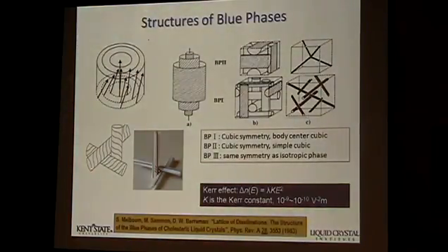So in the past, people very carefully controlled that and studied their physical properties, and they also studied much earlier their electro-optical effects. There are 2 types of electro-optical effects you can expect from such materials. This blue phase material shows a field-induced Kerr effect. What does that mean? The birefringence is a function of applied field strength, proportional to the periodic structure, the elastic constants of the blue phase, and the square of the field. These are Kerr constants, in general in the range of 10 to the minus 9 to 10 to the minus 10 meters per volt squared.